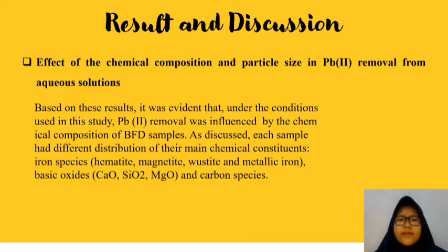Then the effect of chemical composition and particle size on Pb2+ removal from aqueous solution. Based on the results, it was evident that under the conditions used in the study, Pb2+ removal was influenced by the chemical composition of BFD samples. As discussed, each sample had a different distribution of their main chemical constituents, like iron species, basic oxides, and carbon species.